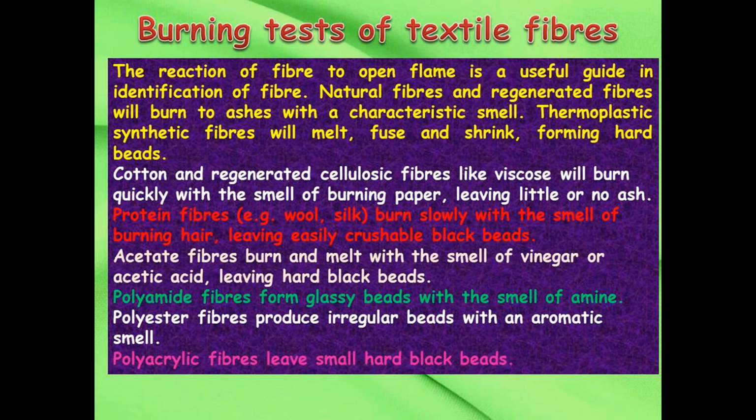Polyamide fiber forms glassy beads with the smell of amines. Polyester fiber produces irregular beads with an aromatic smell. Polyacrylic fiber leaves small hard black beads.